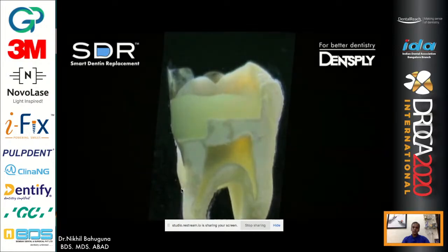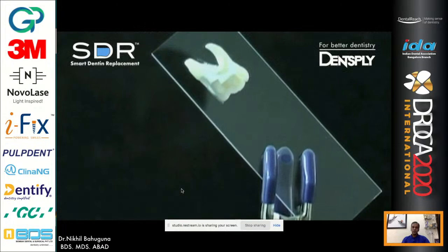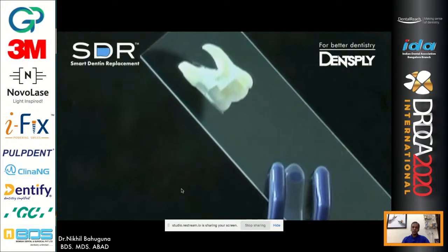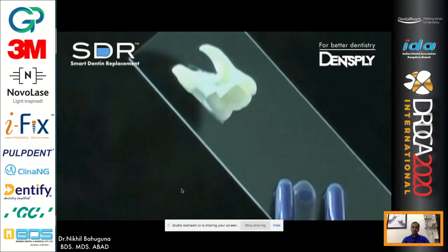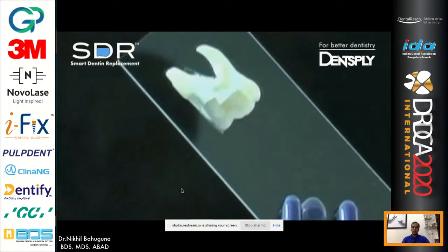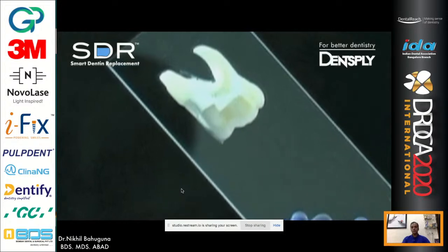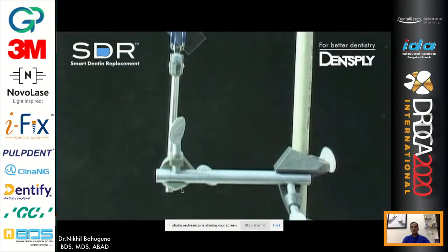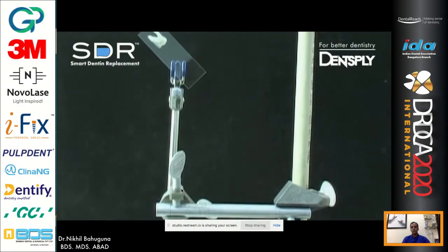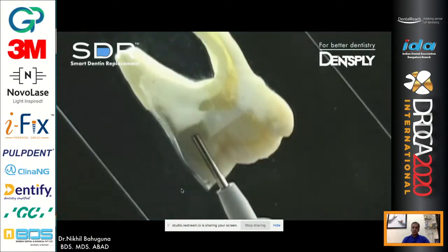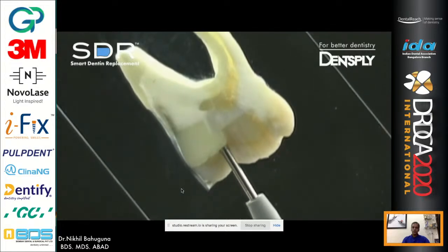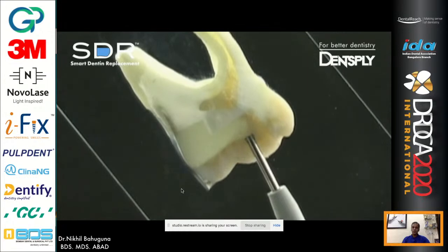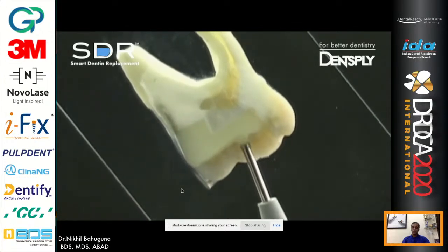Even when you're performing maxillary restorations, to demonstrate, a human molar was prepared for a large Class 2 restoration. The tooth was cut in half and adhered to a standard glass slide. A matrix band was placed to seal the proximal box. The glass slide was positioned at a 45-degree angle to mimic a maxillary restoration. Begin dispensing at the deepest part of the proximal box and watch as SDR self-levels and adapts to the corners of the prep. After dispensing up to 4 millimeters, SDR remains where placed and does not slump or flow out of the cavity preparation, making it ideal for use in maxillary posterior restorations.